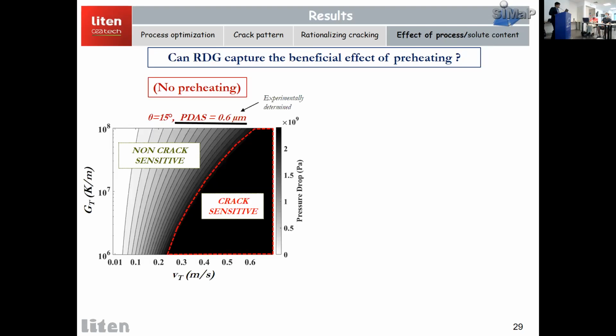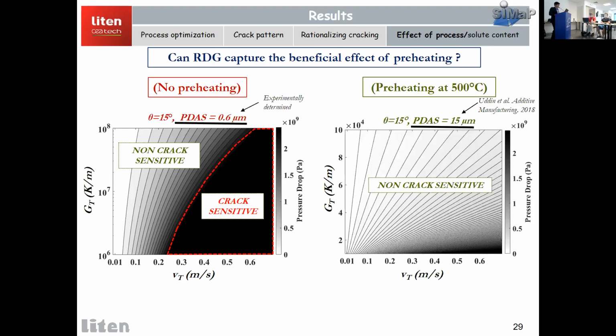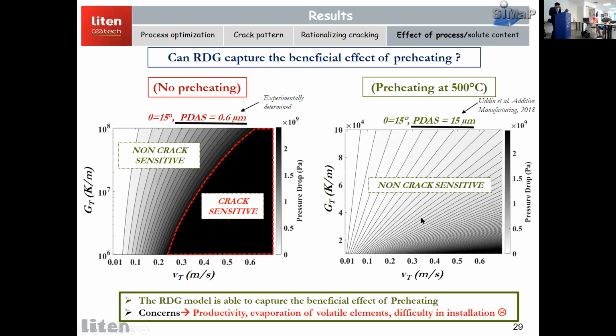So now we implemented these parameters into the RDG model just to see what the model is suggesting. We generated the similar HCS maps for the no preheating condition on the left here. And on the right, we have the preheating condition, where the thermal gradients are largely decreased, taking into account the primary dendrite arm spacing as well. We clearly see that the HCS map on the right for the preheating condition gives us low pressure drops. This indicates that we have a less crack sensitive microstructure. So the RDG model was able to capture the beneficial effect of preheating.